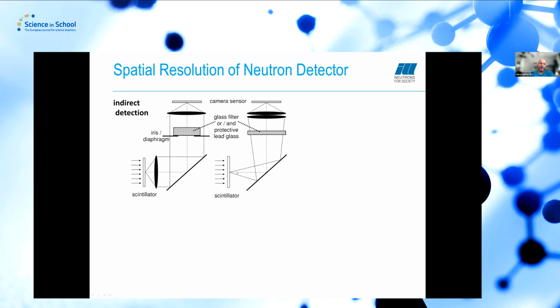You can have two different schemes. One here with a non-infinity corrected setup, where you focus on the screen via one lens or one lens system. Or you can use the infinity corrected approach, where you have a collection lens after the scintillator. And this collection lens gives you a much higher numerical aperture and light collection efficiency than the other approach. So it's more adapted to high resolution imaging. Also, the scintillator must be finer because with this high numerical aperture you are getting less depth of field. That means the scintillator needs to get thinner.